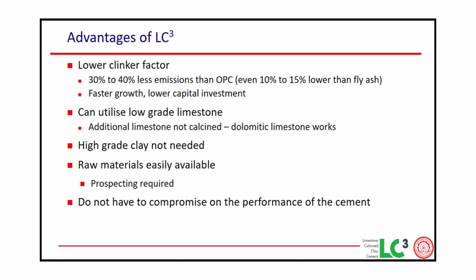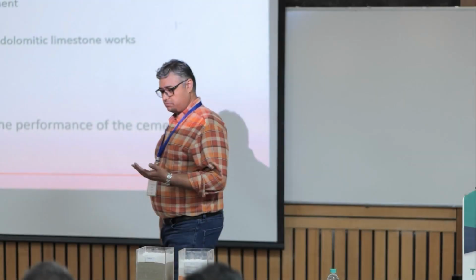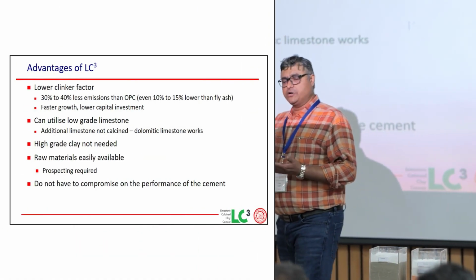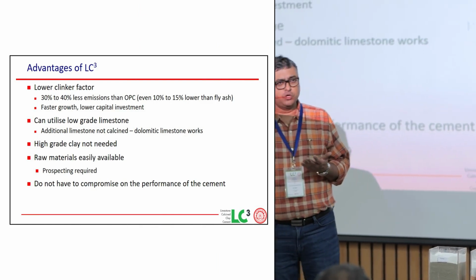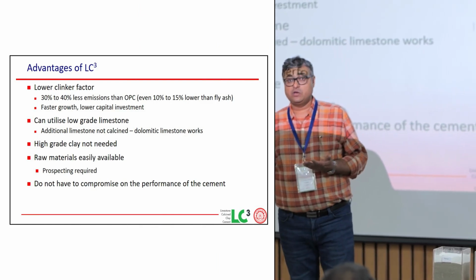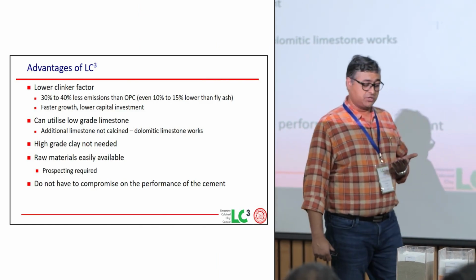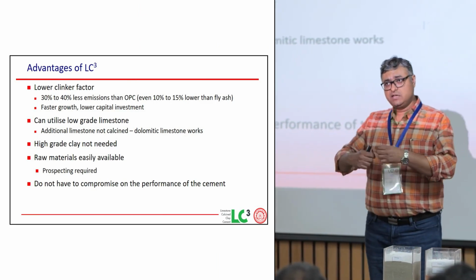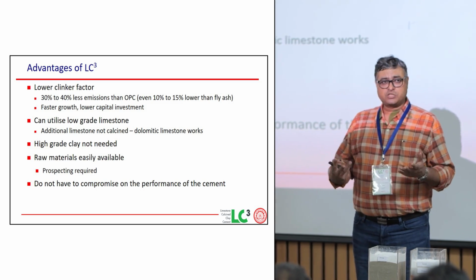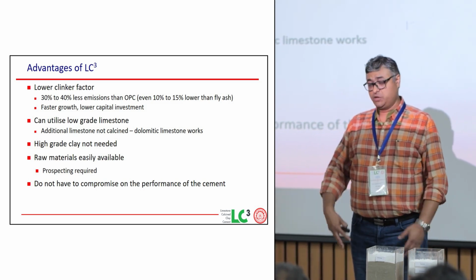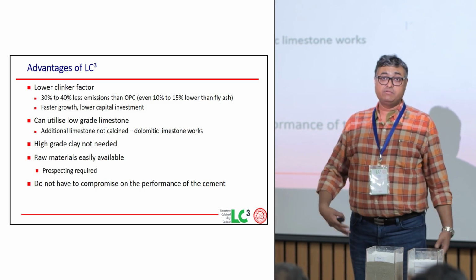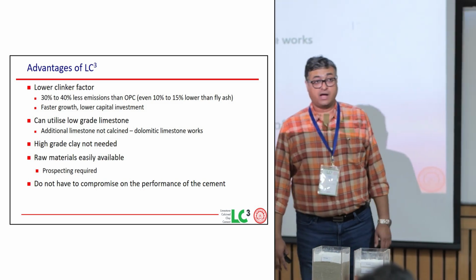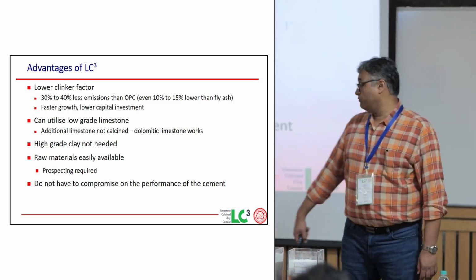There are many advantages. When we looked on paper and looked at LC3, we understood that we are going to have a reduction of the CO2 emission. If you take the back of an envelope and try to do some calculations on how much CO2 you would be saving, you will find that you can save 30 to 40% of CO2 emissions during the production of the cement, and still you will have half the envelope left. Those calculations are very short most of the times, but you can have detailed calculations as well. Somebody will show you tomorrow how these detailed calculations can be carried out and what kind of results you're getting.